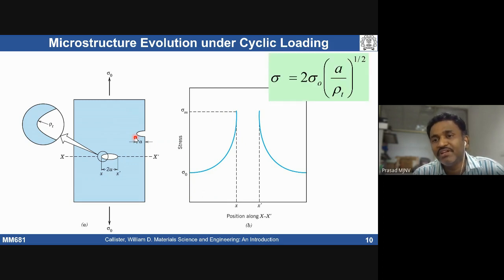So one can estimate the stress in front of the crack tip from how much stress you're applying, sigma naught, the size of the crack a, and rho t, the radius of curvature of the crack tip, raised to about the power 1 by 2. This basically tells how the stress is going to vary depending on the crack size and the radius of the crack tip.